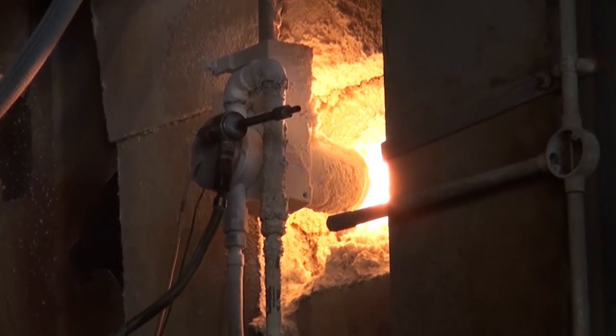In the third section, which is the refiner, the glass basically just cools naturally from 1500 degrees to 1400 degrees, and that's the area where the bubbles rise out of the glass, and at the end of that section you've got refined glass with no bubbles in it.